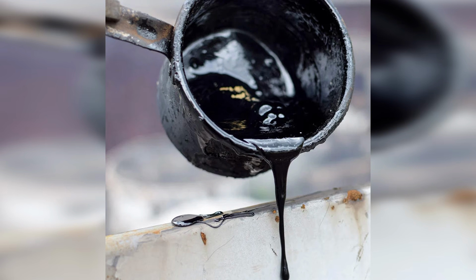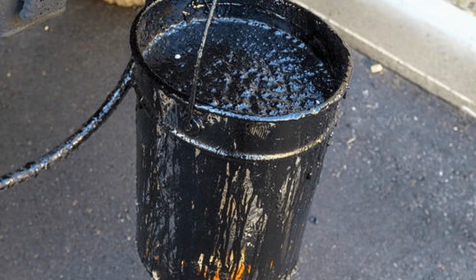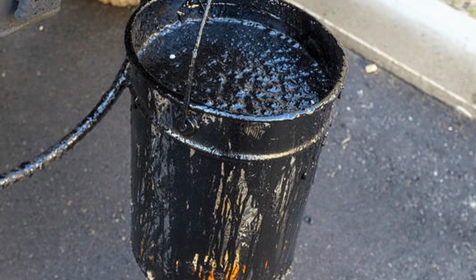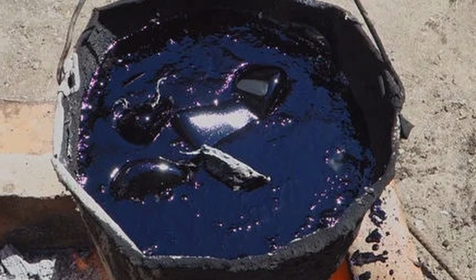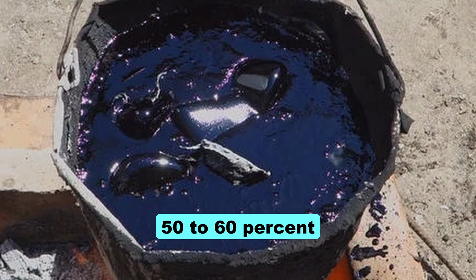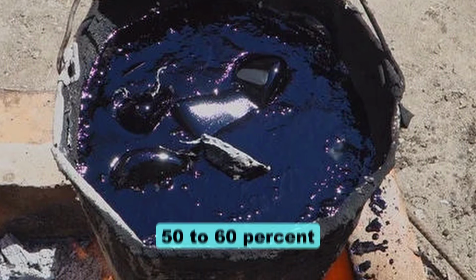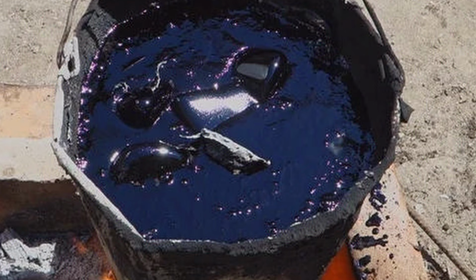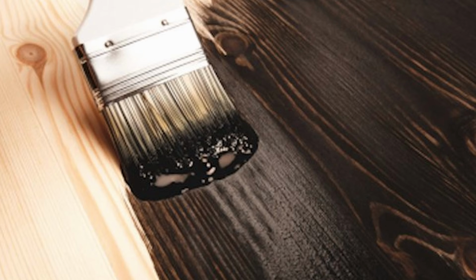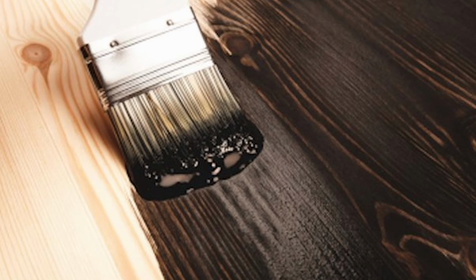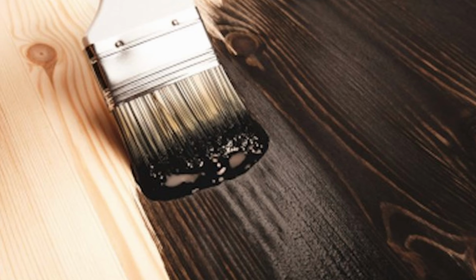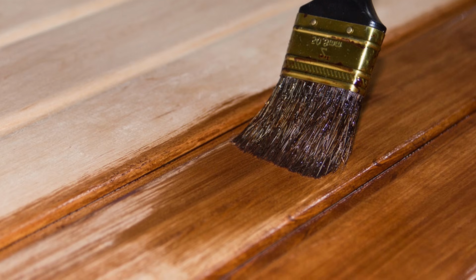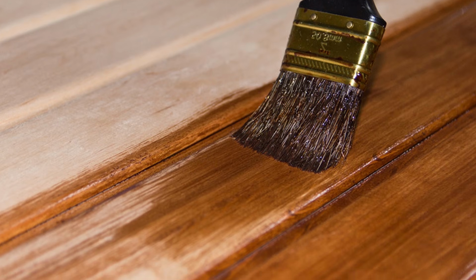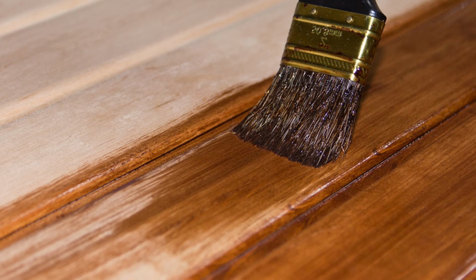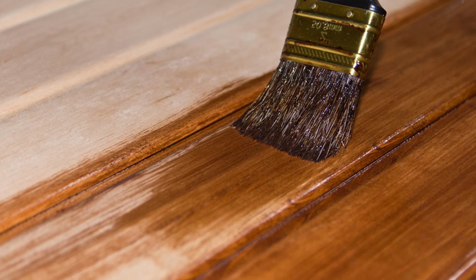The chemistry is remarkable. Pine tar contains 3 types of compounds that work together. Resin acids make up 50 to 60% of the tar. These are hydrophobic, so they repel water. When you apply tar to wood, these acids penetrate deep into the wood pores. Over time, they oxidize and polymerize, forming a flexible barrier that blocks water from entering.